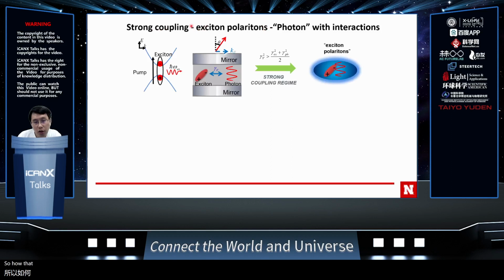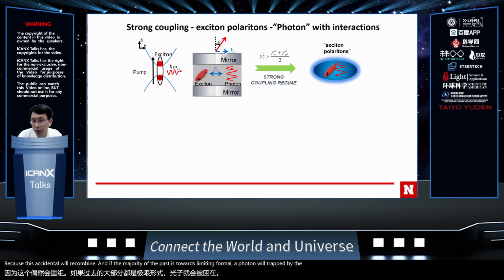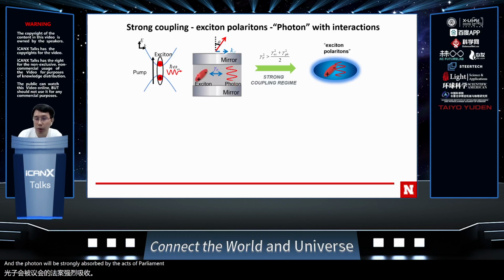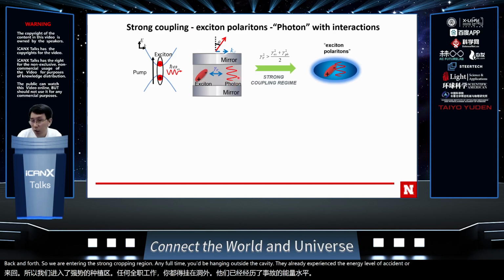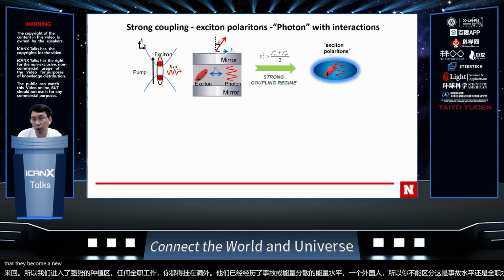So how does that work? Essentially, we start with excitonic semiconductors. If this excitonic semiconductor has a bright quantum yield and strong absorption, you put this strong excitonic material into a good optical cavity, because this exciton will recombine. And if the majority of this path is towards emitting a photon, the photon will be trapped by the cavity. And the photon will be strongly absorbed by the excitonic material again. So exciton becomes photon, photon becomes exciton, back and forth. So we are entering the strong coupling regime. Any photon you detect outside the cavity has already experienced the energy level of the exciton or the energy dispersion of the photon. So you cannot tell whether this is exciton level or photon level. So they become a new quasi-particle called exciton-polaritons.